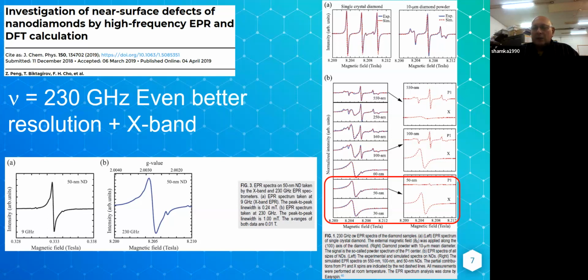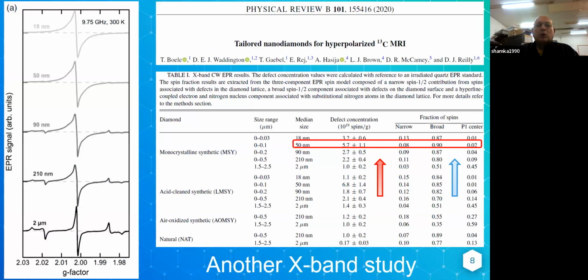Okay, the same. And the last work was done in 2020 by this group. They studied these particles, using these nanodiamonds for hyperpolarized C13 MRI. And as you can see from the spectra, this was also done at X-band at 9 gigahertz. They got the same picture on decreasing the particle size and practically the same numbers. Interesting.